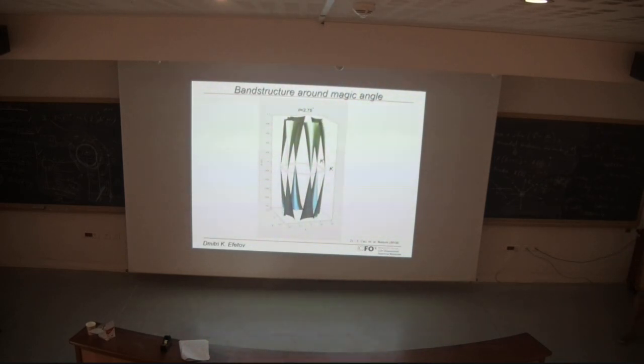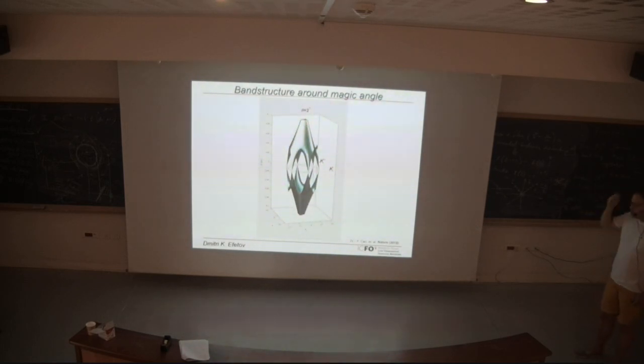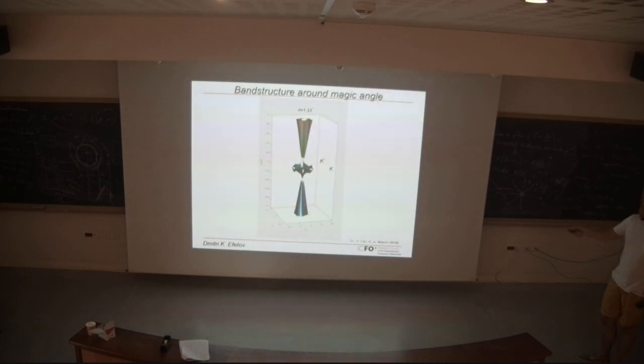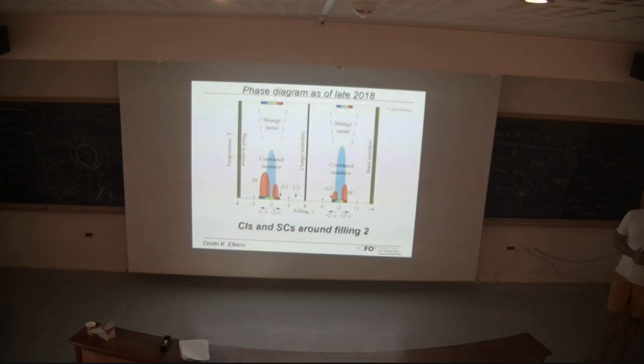But then, as one reduces the twist angle, as you can see, the band structure becomes strongly renormalized, and close to 1.1 degrees, sharply at 1.1 degrees in this calculation, these bands become extremely flat, with a bandwidth of only about 10 meV. Okay? All right. So the picture which is unfolding as of late 2018 is the following: we have these two moire bands, the valence and the conduction bands, each of which can take 4 electrons.